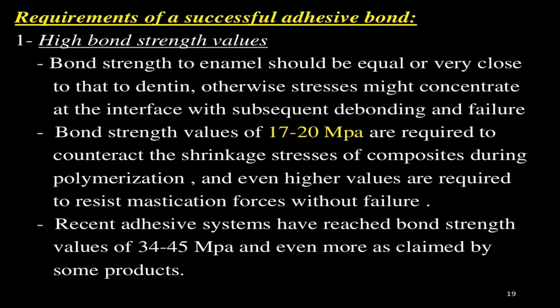Bond strength values of 17 to 20 MPa are required to counteract the shrinkage stresses of composites during polymerization, and even higher values are required to resist mastication forces without failure. Recent adhesive systems have reached bond strength values of 34 to 45 MPa and even more, as claimed by some products.